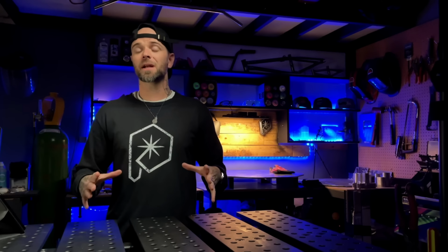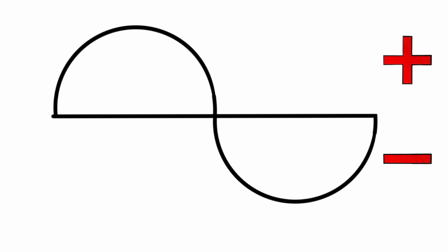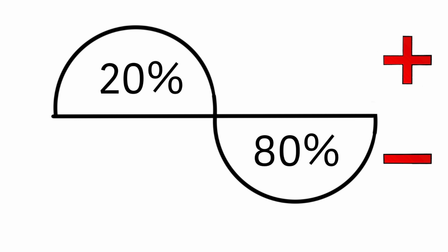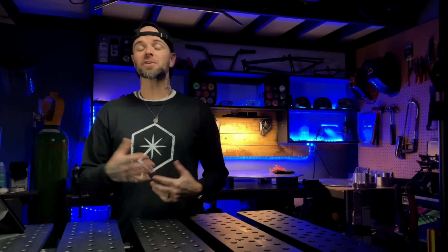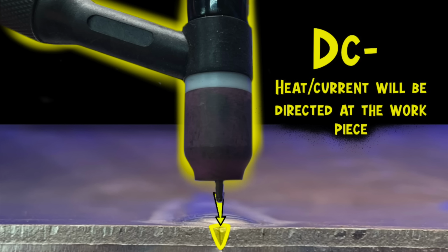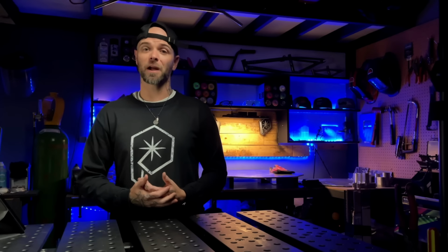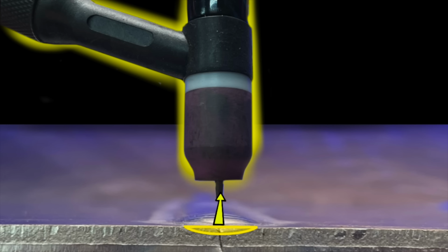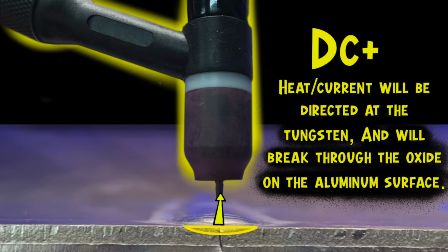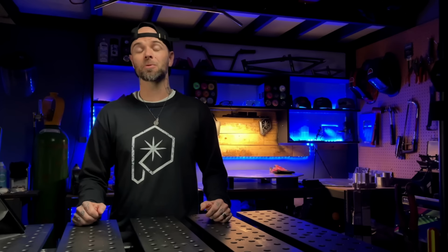So let's take a look at a pretty common setup for balance here. Sometimes when you're setting up a machine, you'll probably be somewhere in the ballpark of approximately 80% on the negative side and approximately 20% on the positive side. So the negative side of our AC cycle is going to do the majority of the actual welding, and essentially how our heat input really affects the base material. The positive side of the cycle is essentially going to be the cleaning side of our polarity. What this side is going to do is direct a little heat back at the tungsten. That's how we're going to keep the tungsten clean, as well as clear away oxide from the surface of the aluminum. And essentially working between these two polarities, this is how it is now possible to weld aluminum.